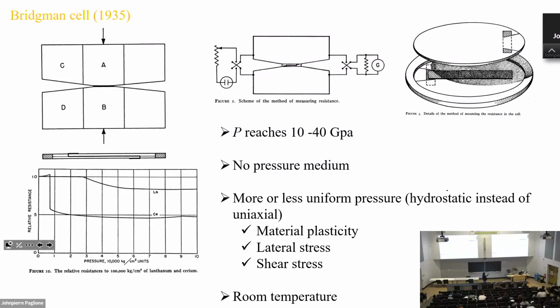And he can get to 40 GPa. The issue is, this setup is only supposed to be used at room temperature. So you have a giant machine to squeeze the sample, to apply the pressure, and they measure resistivity at room temperature. So you can see electrodes are on the anvil cell. You put the sample here, contacts on the other side, then you measure directly from there. So this is a giant machine. And also at the time, this type of cell does not use a pressure medium. So the hydrostaticity is not good, but he assumed the pressure is actually uniform.